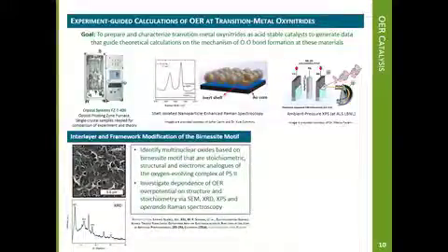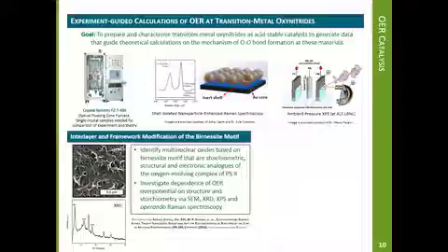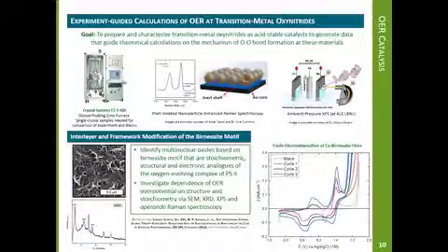Another exciting OER catalyst under investigation is inspired from the heteroatomic manganese complex of photosystem 2 in nature. Birnessite, a layered polymorph of defect-laden manganese dioxide, structurally and compositionally resembles nature's oxygen evolving complex, thereby offering a versatile motif in the search for multinuclear OER catalysts. Strategically intercalated samples of synthetic birnessite can now be prepared using a facile electrodeposition process that reduces the conventional preparation time from 3 days to a matter of minutes.